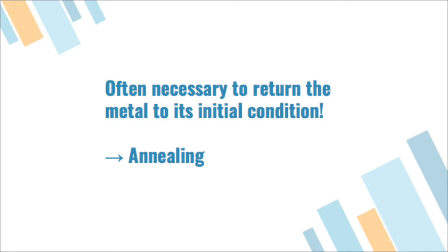So, while the increased hardness and strength that result from the cold working operation can be important sometimes alone, it's often necessary to return the metal to its initial condition by annealing. This usually means holding the cold worked metal at a temperature above about 1/3 of the absolute melting point for a period of time. The annealing treatment is divided into 3 distinct regions.